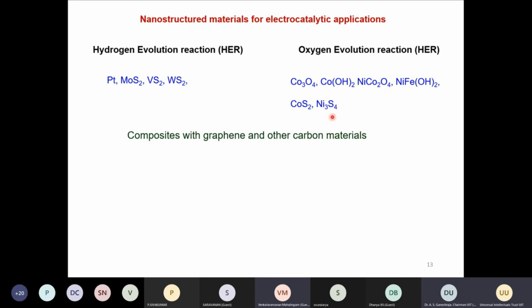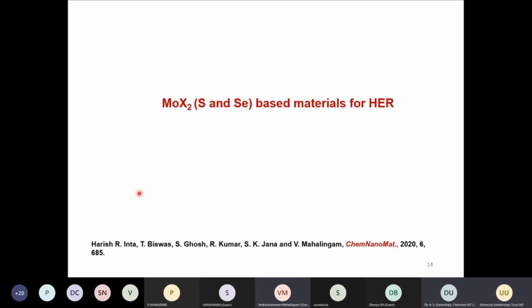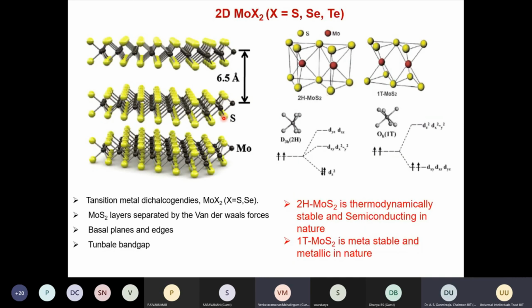What is very important is that we have to make a material which can bring down the overpotential very close to 1.234. So they sometimes combine this with graphene and other carbon-based materials to improve the activity of the material. Today I'll show you a few examples which we have done in our group in the last 4-5 years on the hydrogen evolution reaction and oxygen evolution reaction. This is the work where we have done MoX2, that is molybdenum sulfide and selenium based materials, for the hydrogen evolution reaction.